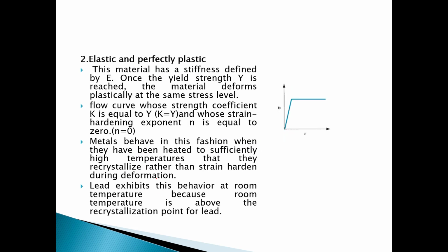Elastic and perfectly plastic. This material has a stiffness defined by Young's modulus. Once the yield strength Y is reached, the material deforms plastically at the same stress level. Flow curve whose strength coefficient K is equal to Y and whose strain hardening exponent n is equal to 0. Metals behave in this fashion when they have been heated to sufficiently high temperatures that they recrystallize rather than strain harden during deformation. Lead exhibits this behavior at room temperature.